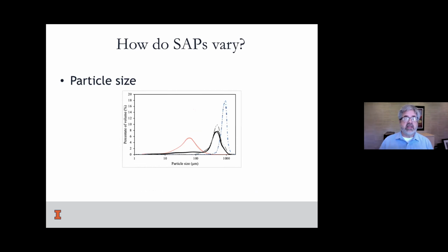Here is one of the reasons that they aren't the same: particle size. We had different samples in our lab that we measured the particle size of, and you can see that this is a fairly dramatic difference between the blue sample up here at around a millimeter versus down here under 100 microns. And so you can imagine that the amount of surface represented by these small particles would be greater, and so the reaction and absorption rates of something small like that would be faster.